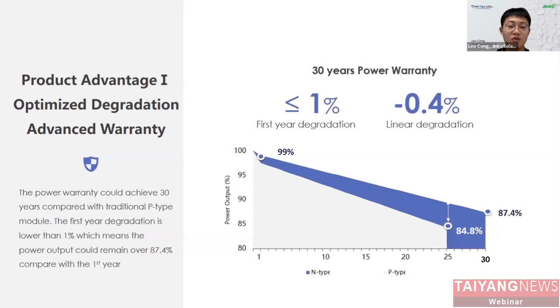technology. And on the more technical side, LID is a loss in the boron-doped P-type silicon solar cell efficiency observed during the initial light soaking process. The boron-oxygen complex activated by carrier injection or illumination was indicated as the root cause, since the boron-oxygen complex captures minority electrons as a recombination center. Even hydrogenation cannot totally passivate the boron-oxygen complex defects. I mean, the N-type cell uses a phosphorus-doped process, with no boron-oxygen related LID, and also no degradation by initial